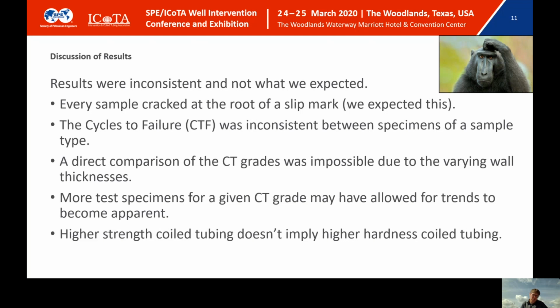But the bottom line, based on the results that we saw here, is that higher strength coil tubing doesn't imply higher hardness, which was quite a shock for us because the mechanical engineer in me is screaming, wait a minute, there's a well-established correlation between yield strength and hardness, and based on these samples, we didn't see that.